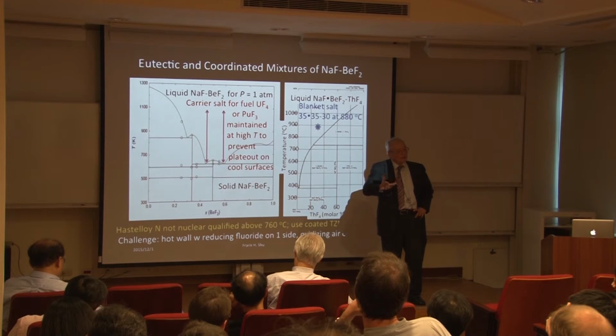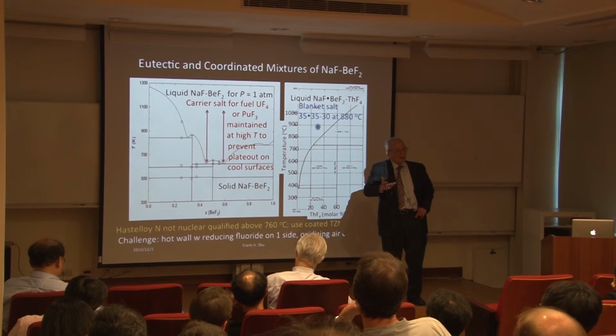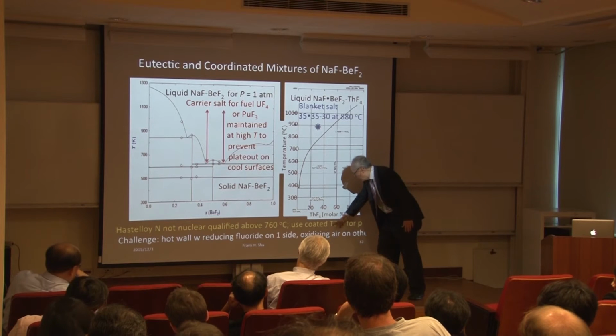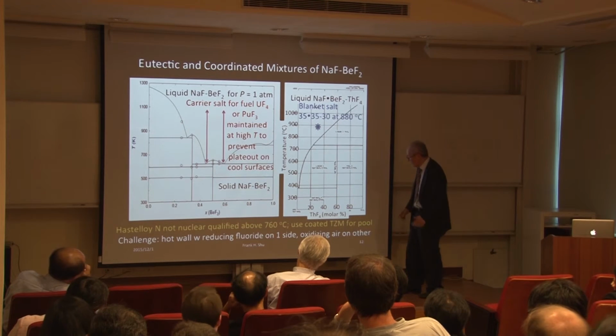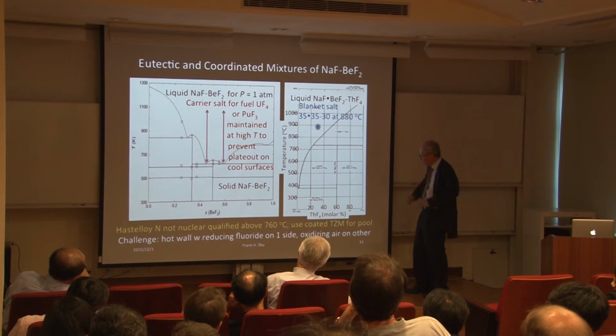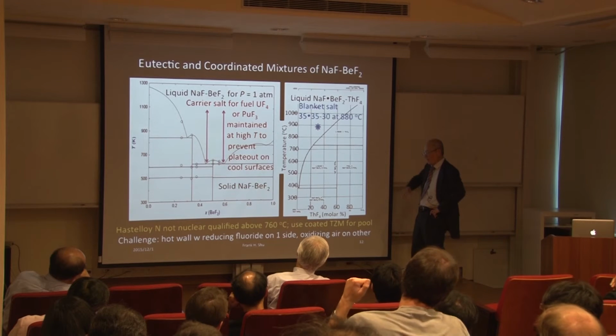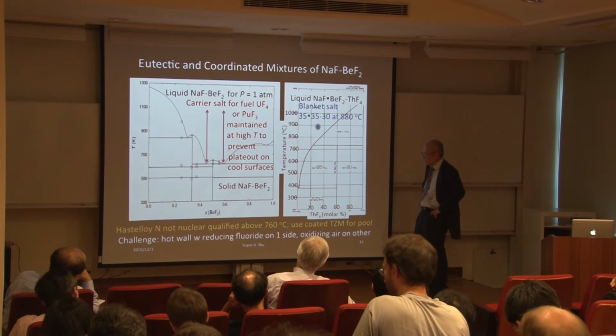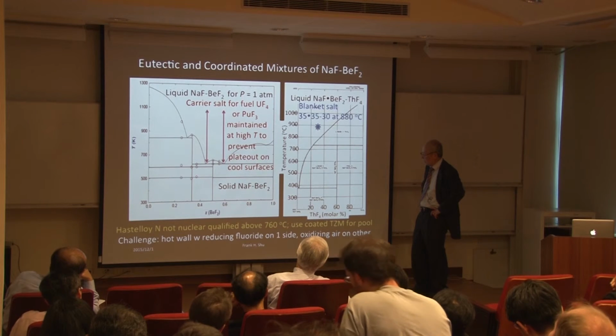It's also, since it's almost like a ceramic, easy to break. So it's not easy to fabricate. Okay. So people put 1% of titanium and zirconium into molybdenum to make it so you can fabricate things with it. But you still have to deal with the fact that on one side, it likes to be attacked by fluoride. On the other side, it likes to be attacked by oxygen.